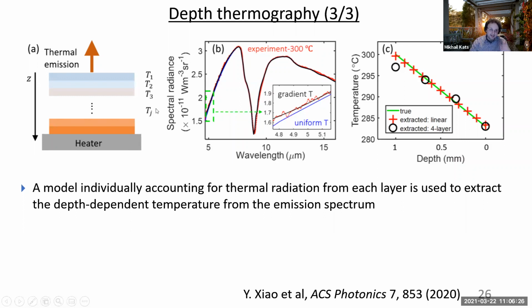And so what we did instead is we built a model. Rather, Yuja built a model, which is essentially a thin film model where you're taking this object, which is just a single homogeneous object, but you're discretizing it into many, many thin films. And you're assuming that the optical properties of each layer are the same, but the temperatures are slightly different. And we don't necessarily know what those temperatures are, but they're different. And so that allows us to try different combinations of different temperatures of these layers, and then to see if we can match the experimental curve better. And if we can match it better, then we're assuming that this is a better prediction or guess of the temperature distribution than just assuming that all of the temperatures were the same.